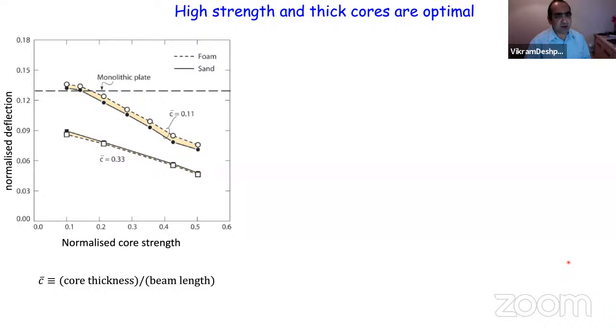Why is it that high strength thick cores are optimal for this particular application? So these are simulations now of normalized deflection as a function of this core strength, and we are showing these simulations for 2 different values of the thickness of the core. So C bar is the thickness of the core divided by the beam length. And what you can see is that as you increase the core strength for a given thickness of the core, the deflection keeps decreasing. And of course, if you increase the thickness of the core, keeping the mass the same, i.e. you've thinned the faces to compensate for that, you basically again get the same trend, but the deflection of the beams is low, which is consistent with those experiments that I had just shown you on the previous slide.